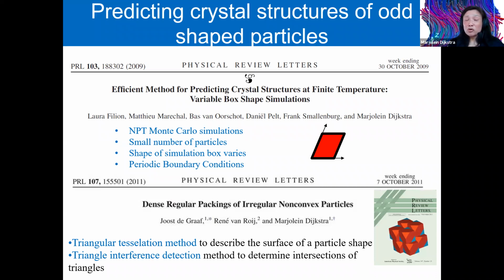And then by just using the isobaric-isothermal ensemble, so we fixed the number of particles and the pressure of the system, we could slowly increase the pressure to find the densest packing, or we could slowly decrease the temperature in order to find the ground state structures. And later on, we combined it with a triangular tessellation method and a very fast triangle intersection detection method in order to describe the surface of any particle shape.